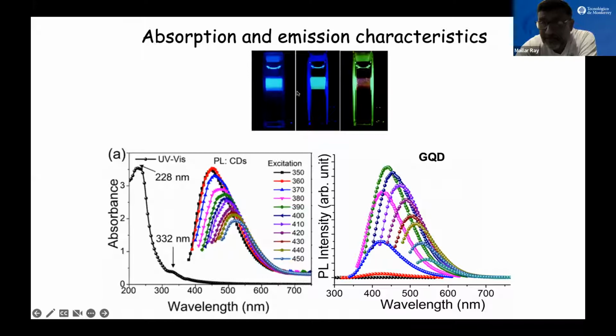But if we change the excitation energy, if we reduce the excitation energy from ultraviolet to blue to green, we can essentially tailor the output emission that we get from these carbon dots, all the way from blue to nearly red emission. That's what we see in the picture, and that is also what is reflected in the emission spectrograph.